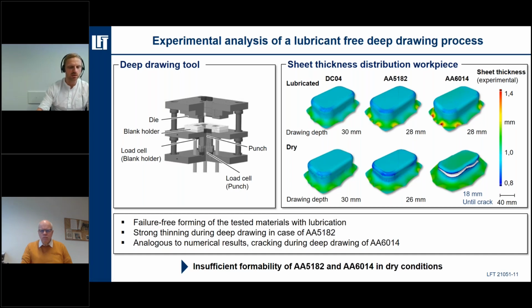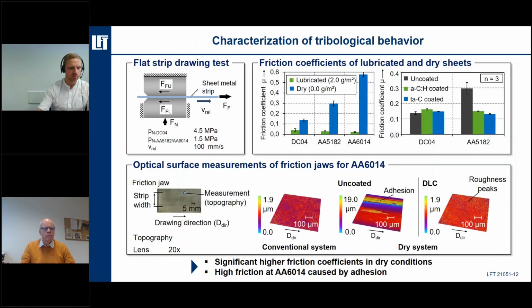A strong thinning during deep drawing occurred in the highly stressed corner radii at a drawing depth of about 26 millimeters. In case of AA6014, an earlier cracking could be identified at a drawing depth of 18 millimeters. So the experiments told us that they are in accordance with the numerical simulations. However, without lubricants or coatings, there is a high chance to expect material failures and crackings while forming, especially for these aluminum alloys. So for this purpose, in the next step,